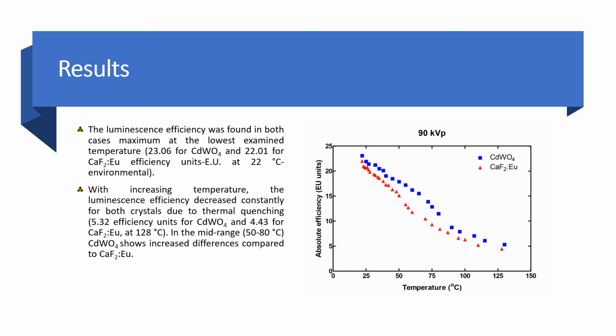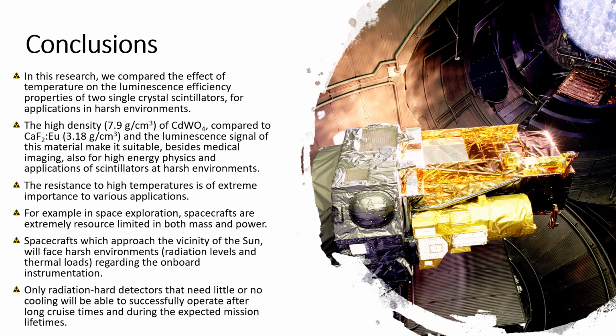With increasing temperature, the luminescence efficiency decreased constantly for both crystals due to thermal quenching. That is 5.32 efficiency units for cadmium tungstate and 4.43 efficiency units for calcium fluoride doped with europium at 128 degrees Celsius. In the mid-range, cadmium tungstate performs much better compared to calcium fluoride doped with europium. Concluding, in this research, we compared the effect of temperature on the luminescence efficiency properties of two single crystal scintillators for applications in harsh environments.